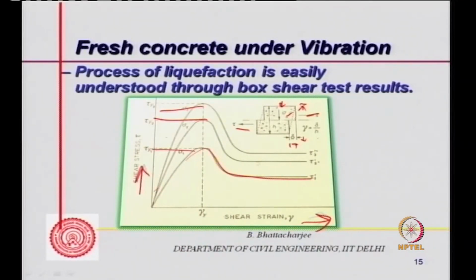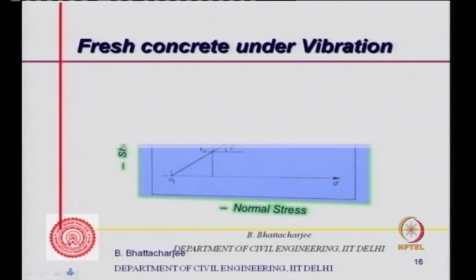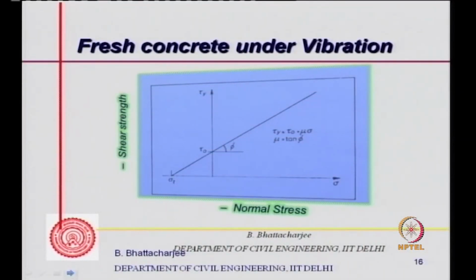So as you increase the normal force, the yield shear stress actually increases. Higher normal force, yield shear stress increases. So for concrete, people have done box shear tests, and this is the kind of behavior which normally one would see. And like soil, you can put shear stress versus normal stress, and it can be related linearly.